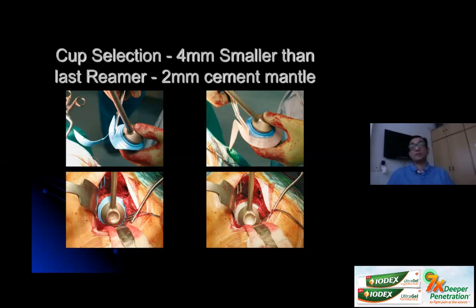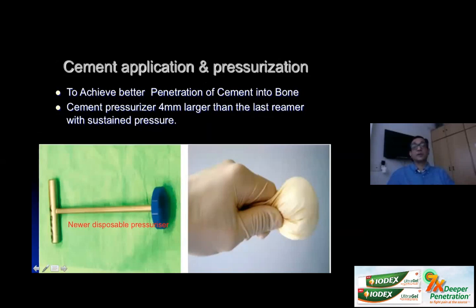If the flange is very big, I will trim the flange, put the cup, do a trial reduction of the placement of the cup, and mark that position with methylene blue before I start mixing my cement. The cup is then washed and dried, and then I start mixing my cement. And the next step would be to pressurize this cement.